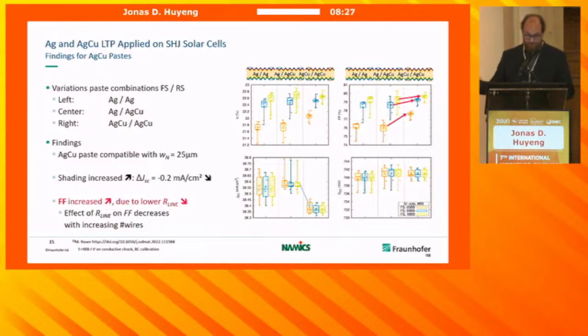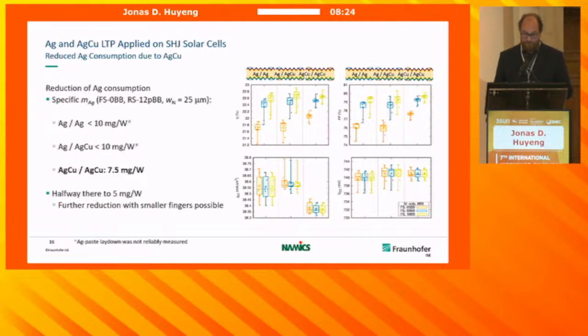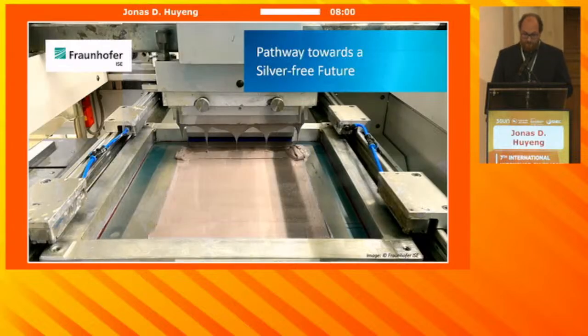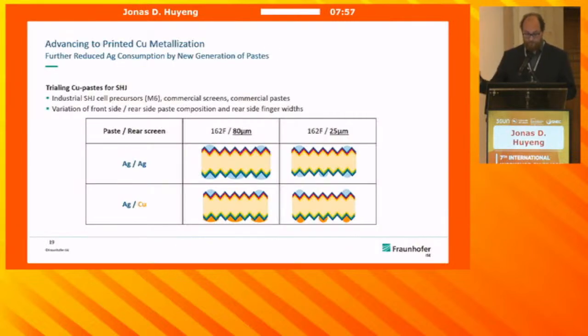And then in terms of the silver reduction, we can then convert this all to milligrams per watt. And while there's been some challenges in the lab for these groups, we can already see that silver copper on both sides brings us halfway to the 5 milligrams per watt target that we have. And if we can optimize this further, going further into fine line printing with these materials, there's of course more potential to have. And then, of course, we would like to go the full way, replacing with fully copper material, at least testing where we are with this technology at the moment.